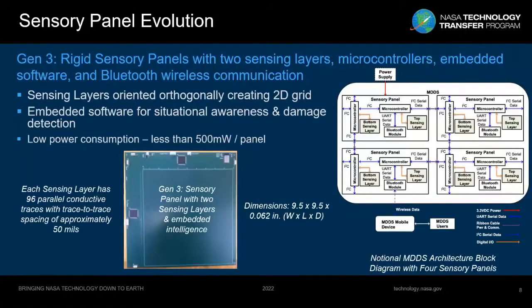The Generation 3, we decided we focused a lot more on the embedded software and instead of on the sensing layers. And so we actually designed a system that has a 2-layered sensory panel that has everything on board, including the microcontrollers, the embedded software, and the Bluetooth wireless communication. An image is shown here of the 2 sensing layers. They're orthogonal to give us a 2-dimensional grid. Each sensing layer has 96 parallel conductive traces, and the spacing between is roughly 50 thousandths of an inch.